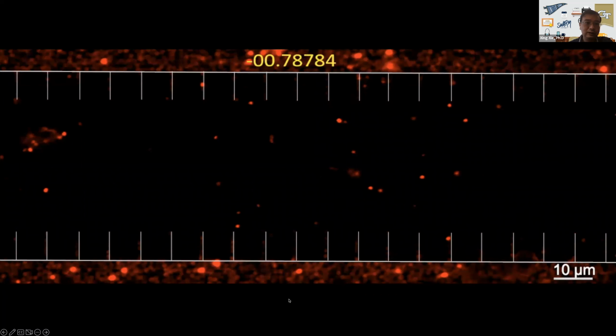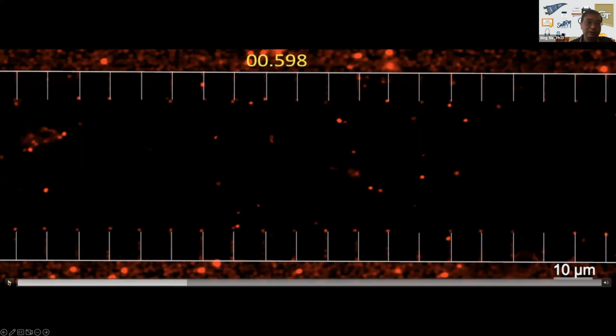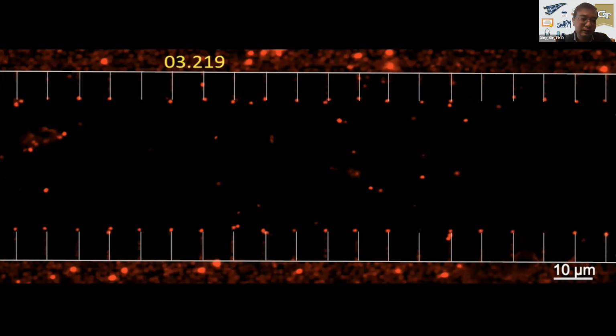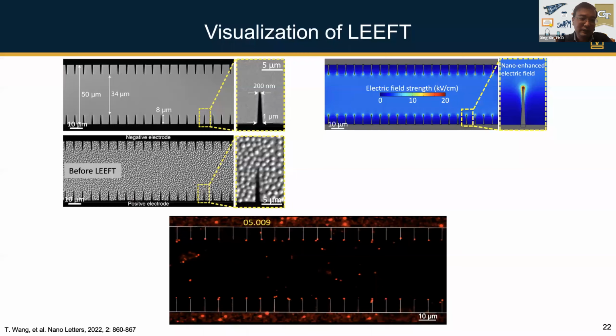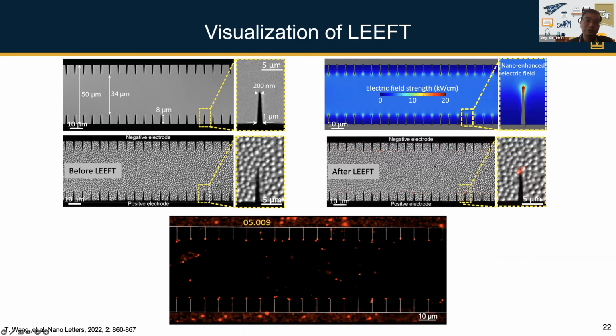So see, now basically when the time gets to about past the 0, you will start to see some red dots show up, right? So some of them show up here. And then when the time goes by, you will see more and more of these bacterial cells near the tips of these nano wedges get inactivated, and then they will get this red color. This is basically, we do some image processing. We remove the background noise information, and then you will see that most of these cells are at the tips of these nano wedges, they get inactivated.